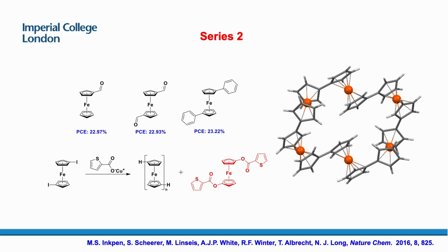And so we looked around our lab, and for those in the audience, the chemists again will know this material. This is a compound we published in Nature Chemistry in 2016, and one of my students was trying to reproduce this material using this equation down here. And this is where serendipity, the beautiful serendipity of science, comes into play. She was making this, this is what she was trying to make, but this material next to it was a byproduct in red. This was a byproduct that she kept getting. So we had lots of this byproduct that we weren't doing anything with. So I thought, actually, looking at some of the groups on this byproduct, maybe this could be useful for perovskite.